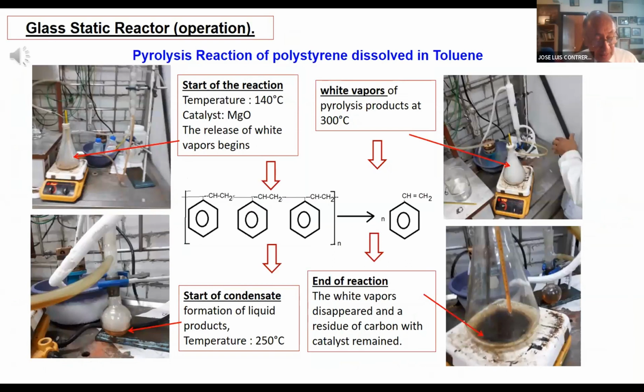Following the pyrolysis reaction of polystyrene in toluene, the beginning of the formation of white vapors is observed at 140 Celsius, while the production of condensate is observed at 250 Celsius. For a longer time, at 300 Celsius, the presence of white vapors continues in the reactor until the presence of these vapors ends. A black carbon liquid solid is found at the bottom of the reactor.